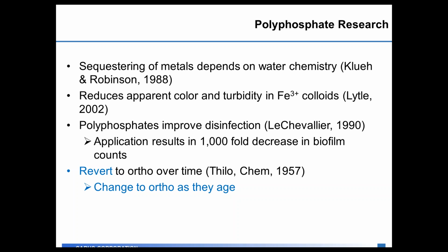The research also shows that as you apply a polyphosphate to the water, it reduces the apparent color and turbidity, specifically for iron and manganese out there in the distribution system. Polyphosphates have been shown to improve disinfection in the distribution system. One of the things polyphosphates will do is they'll sequester metals from that tuberculation and scale in the distribution system, and that allows your chlorine to more effectively attack the biofilms out in the distribution system.